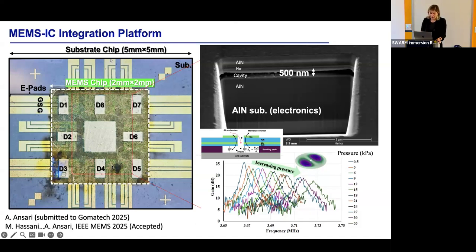And on the left-hand side, you can see that you have your aluminum nitride substrate, and this is the MEMS die where the silicon is removed. So there are 8 pressure sensors, all on the MEMS chip, that are flip chip bonded with better than a micron resolution to your substrate. So this is work in progress. We have only tested these up to 350 degrees C. We're looking forward to higher temperature measurements, which is when things get more complicated.